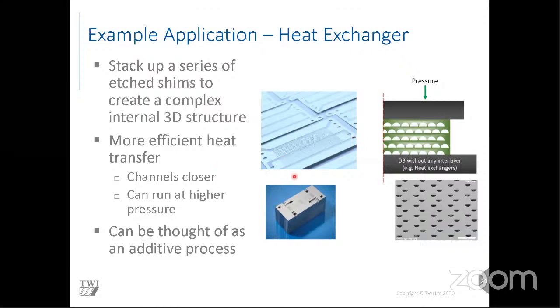We stack these together, and when you diffusion bond it, you get a complex 3D structure, as you can see in the bottom left. These compact heat exchangers have advantages over traditional tube-to-tube sheet heat exchangers because the channels are closer. If you look on the bottom right here, this is a micrograph of this heat exchanger, and you can see how close the channels are. So this layer here will be the hot fluid, the layer below will be cold fluid, and vice versa.